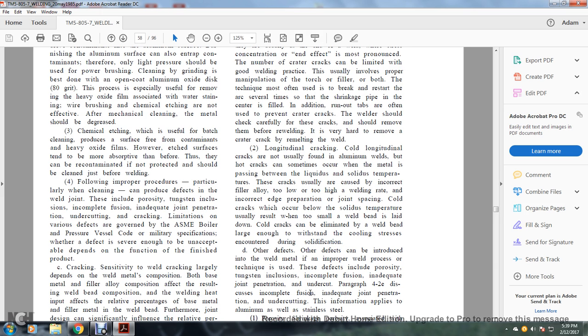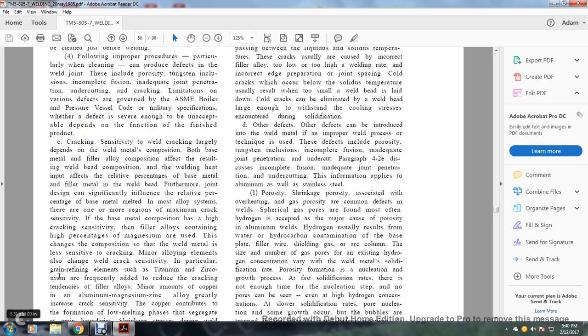The defects of the welding joint include porosity, tungsten inclusions, incomplete fusion, inadequate joint penetration, undercutting, and cracking. Limitations on the various defects are governed by the American Society of Mechanical Engineers Boiler and Pressure Vessel Code and military specification. Whether a defect is severe enough that it is unacceptable depends on the function and finish of the product.